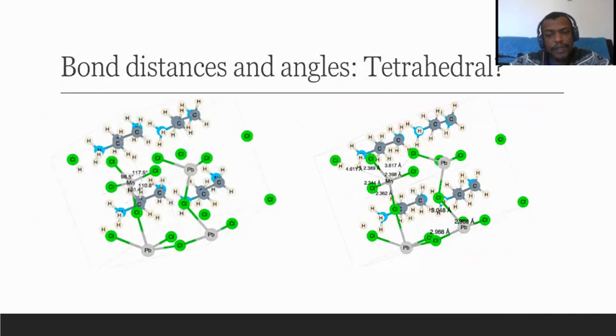So here, and in the previous slide also, the band gap was very, very small, which would translate into a PL of close to 1,000 nanometers, which is not what we expected. So what I did was to measure bond distances and the angles, to understand if something happened during the geometry optimization or something like that.